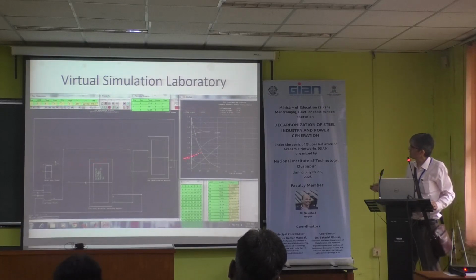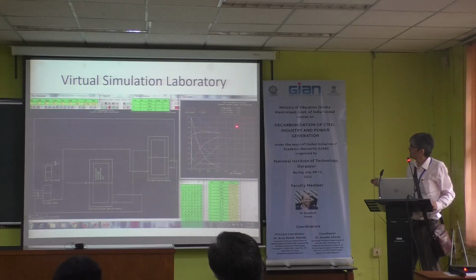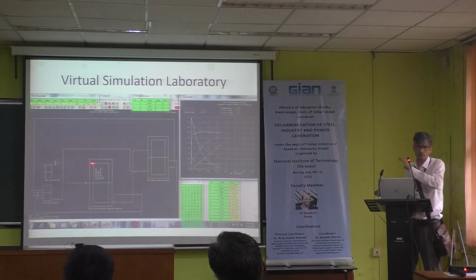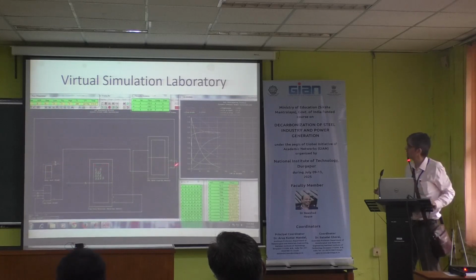So for the oxygen steelmaking process, the behavior of the reactor in terms of the evolution of carbon, silicon, bath composition, slag composition, volume of the slag, and waste gas could all be estimated by applying a similar approach. In fact, most of the information is available on my YouTube. I have made these calculations, and one can just have a look at it.